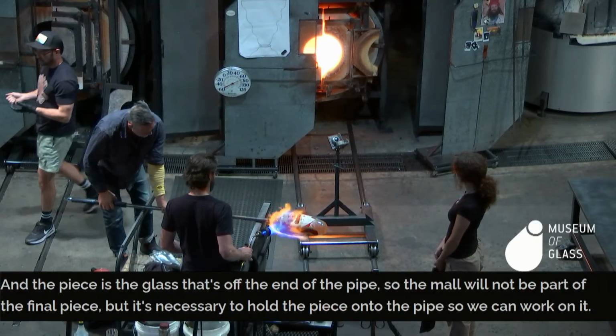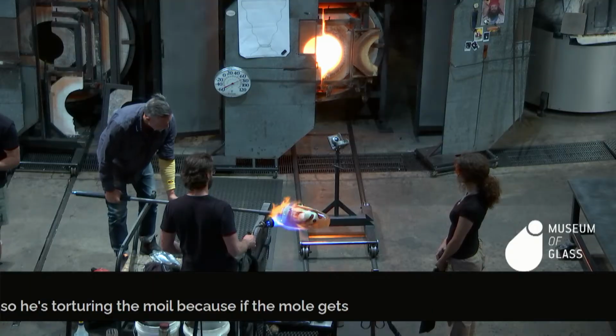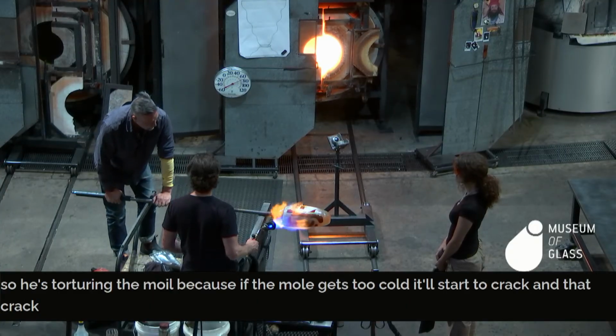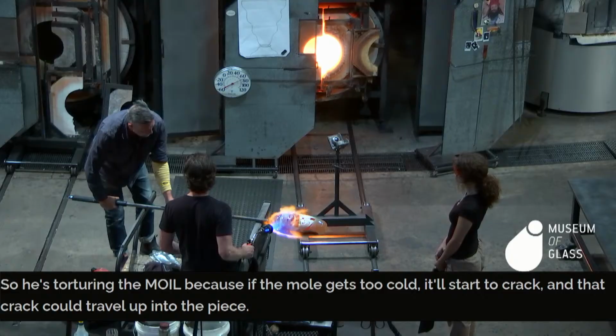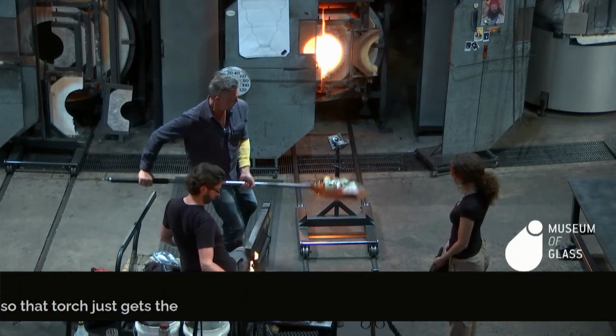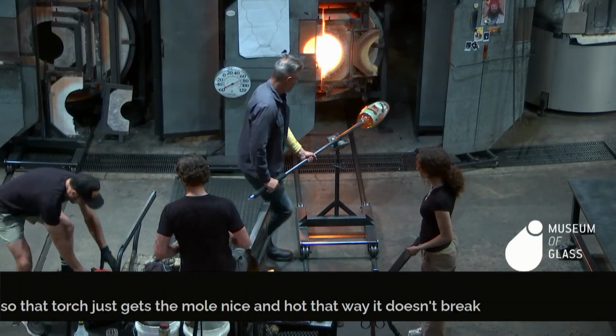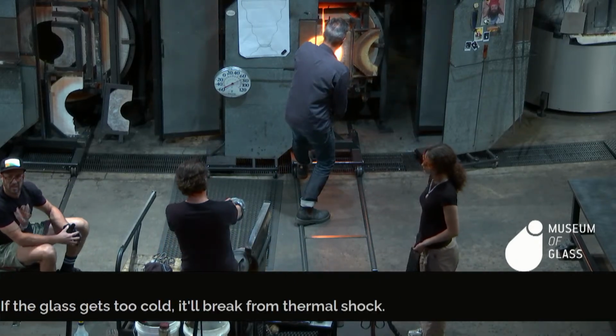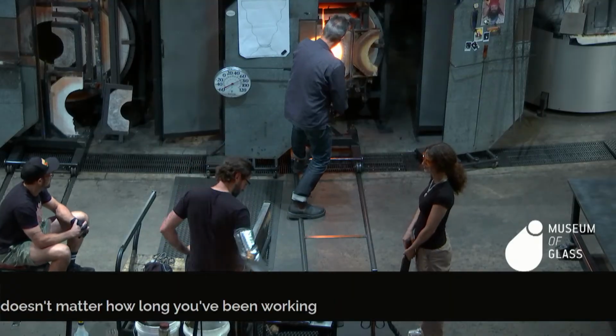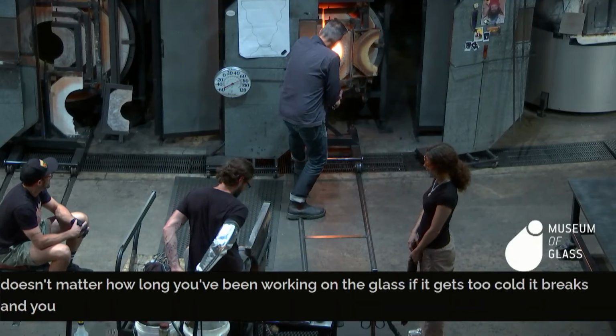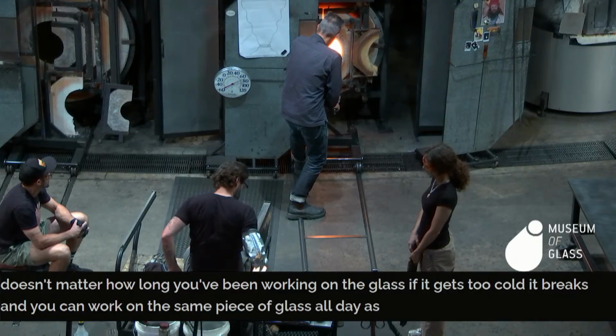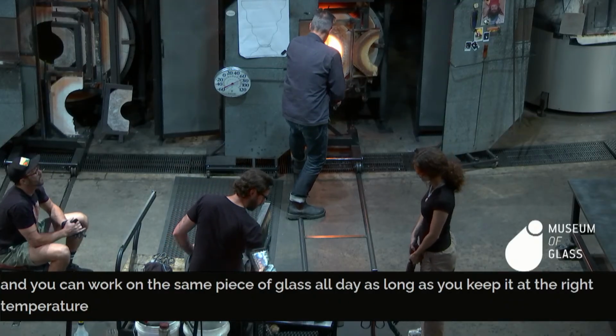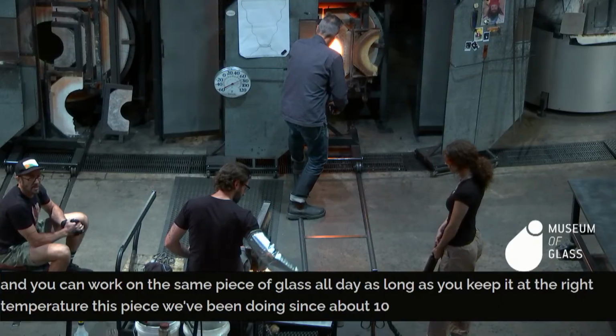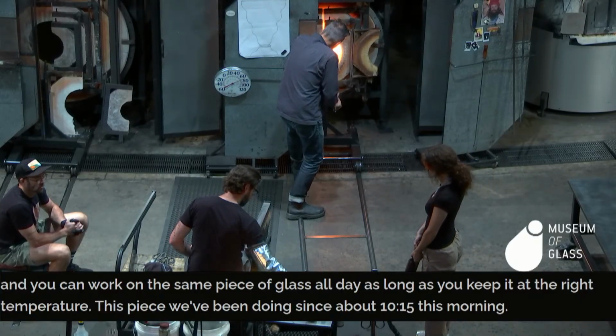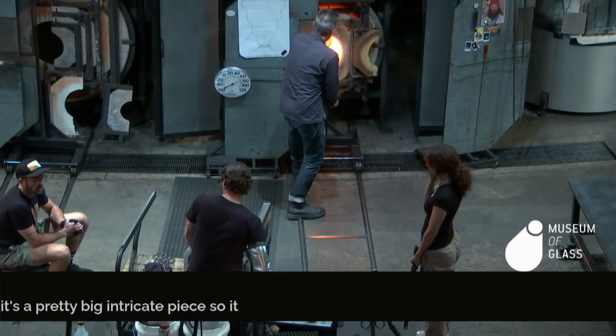So he's torching the moil because if the moil gets too cold, it'll start to crack, and that crack could travel up into the piece. So that torch just gets the moil nice and hot, that way it doesn't break. If the glass gets too cold, it'll break from thermal shock. Doesn't matter how long you've been working on the glass, if it gets too cold, it breaks. And you can work on the same piece of glass all day as long as you keep it at the right temperature. This piece we've been doing since about 10:15 this morning. It's a pretty big, intricate piece, so it'll take a couple of hours probably.